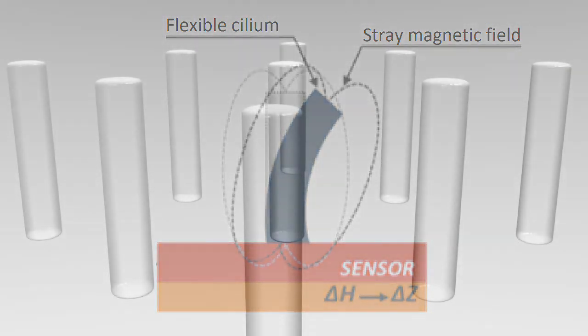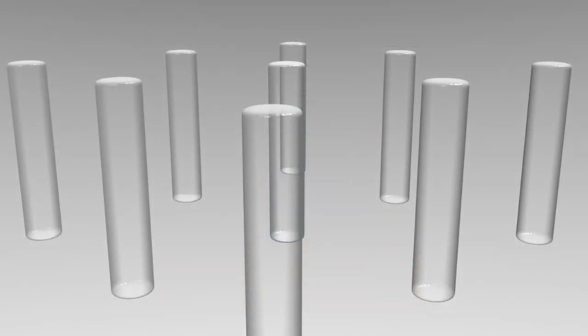The chosen setup for my project was to pattern iron nanowires, that are long iron cylinders, with nanometric diameters embedded in PDMS nanorods, a quasi-perfectly elastic material, in order to obtain flexible nano-pillars with permanent magnetization.